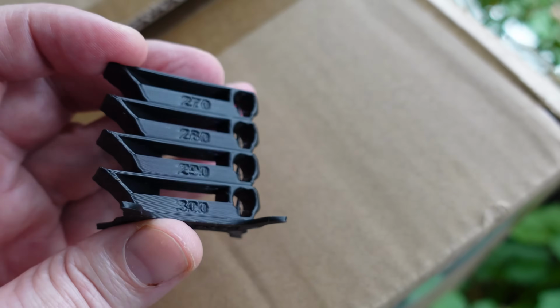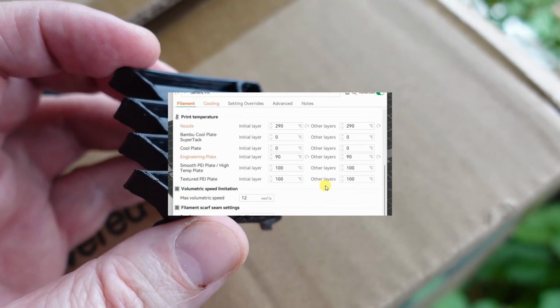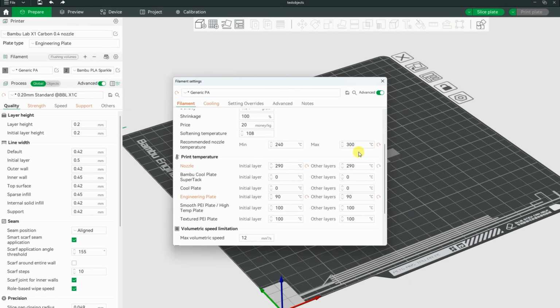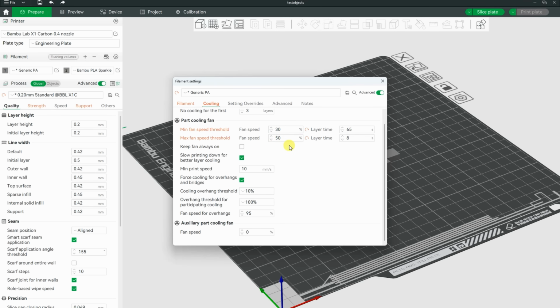So I print everything at 290 degrees Celsius. The base is the generic PA profile. I modify the nozzle temperature to 290 degrees Celsius, the flow rate as well, and the part cooling between 30 and 50%. Last few vertically printed objects.